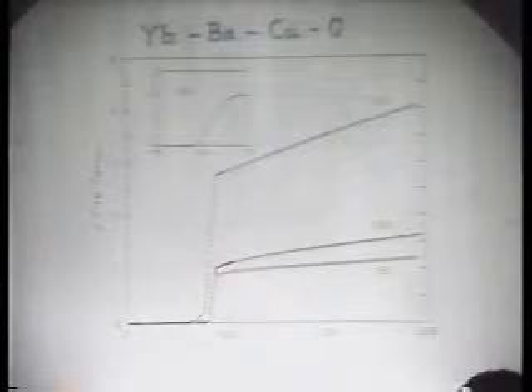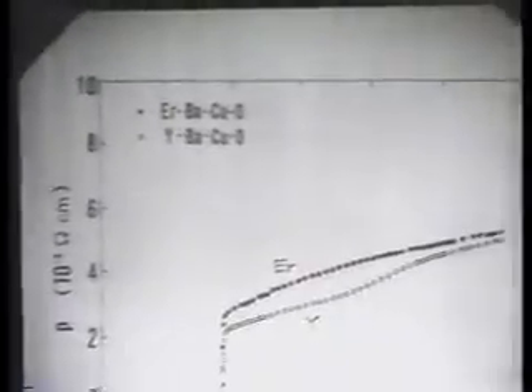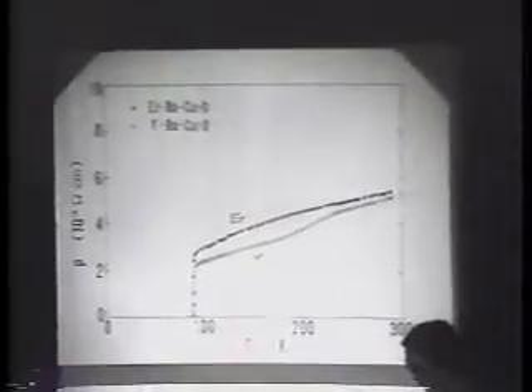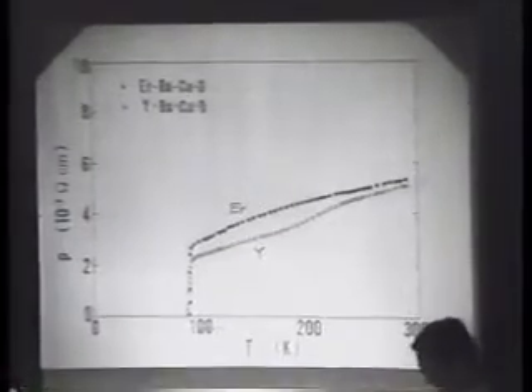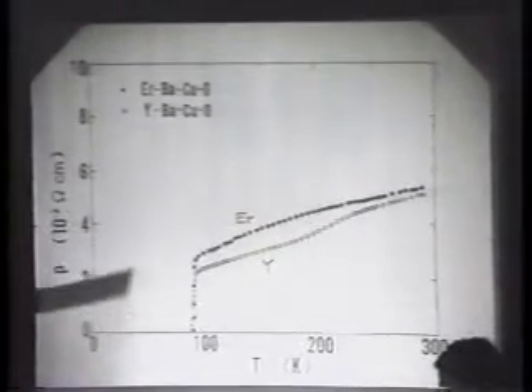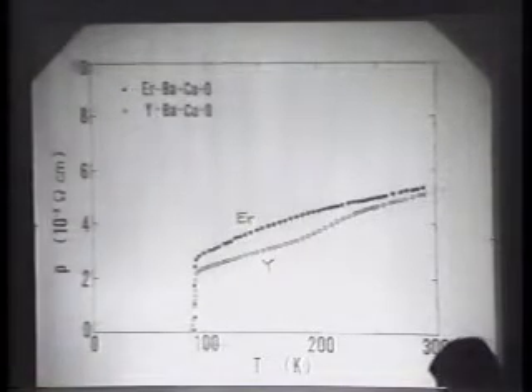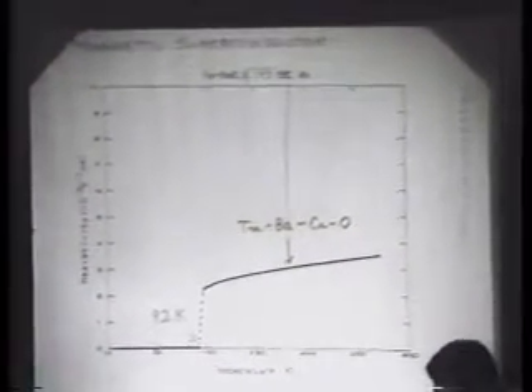Now we proceed to new materials which were found by Japanese groups. We replaced yttrium by other lanthanide elements such as ytterbium, erbium, holmium, and dysprosium, and found that all of them showed a high TC of 90 degrees Kelvin. They have the same X-ray pattern as yttrium barium copper oxide. I will show you some of the data as follows. Yttrium, erbium, dysprosium, and so on.